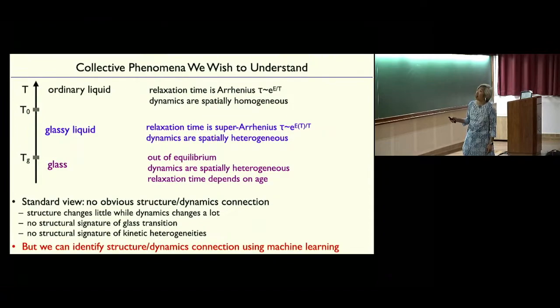So at a high enough temperature, you have an ordinary liquid. What we mean by that is that the relaxation time, for example, has the expected dependence on temperature just from having an energy barrier: e to the energy barrier over temperature.